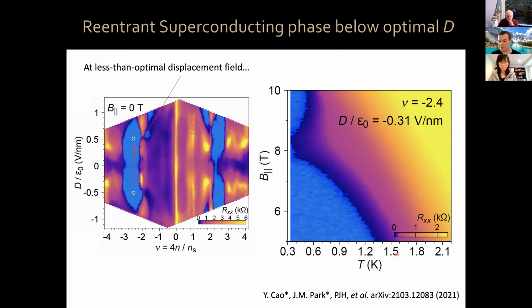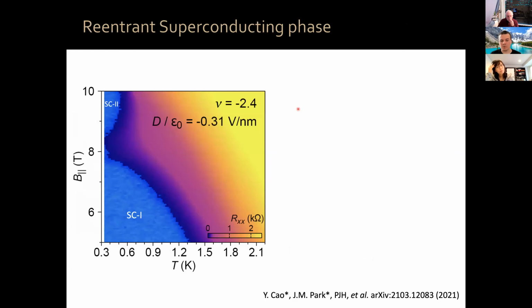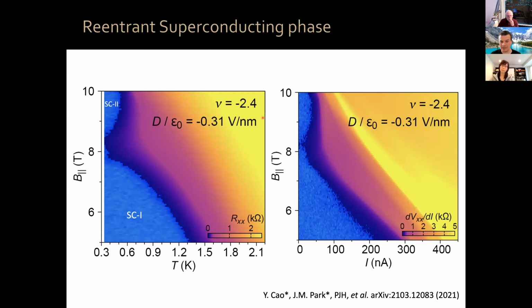We see that our resistivity decreases, our critical temperature decreases continuously until it goes to 0. And then another superconducting dome emerges at high magnetic field, okay? We call that superconducting 1 and superconducting 2 regions, okay? We see this not only in the critical temperature, but also in the BKT temperature, we see it also in the critical current, okay?